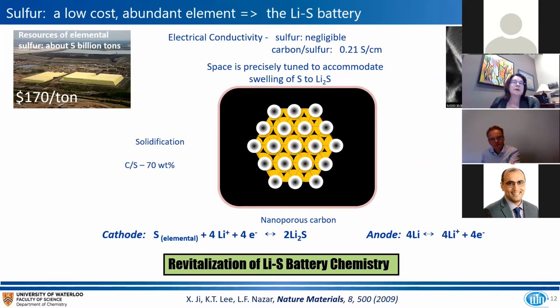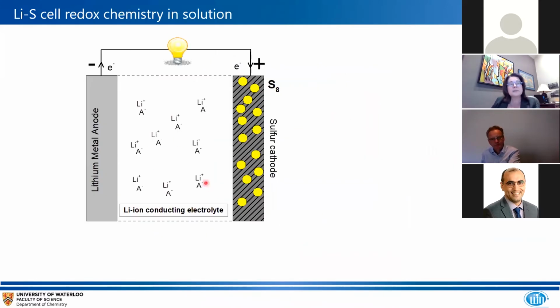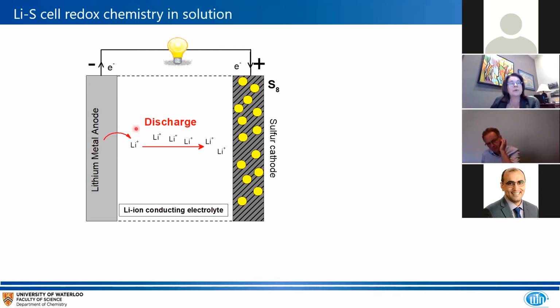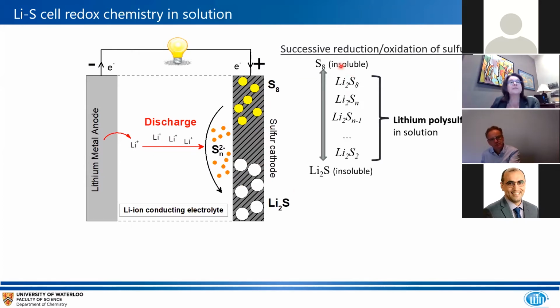What we didn't realize at the time was that carbon was really not the ideal host, unfortunately. And this is because lithium sulfur batteries operate on the process of dissolution of polysulfides. So the lithium from the anode gets basically oxidized into the electrolyte, and the sulfur at the positive electrode gets converted into polysulfides. And there's a whole sequence, a chain of command, as one goes from sulfur, which is insoluble, to Li2S, the end member, which is also insoluble, but the intermediates are quite soluble. And this is sometimes referred to as cheese to milk back to cheese conversion because of this solubility problem.